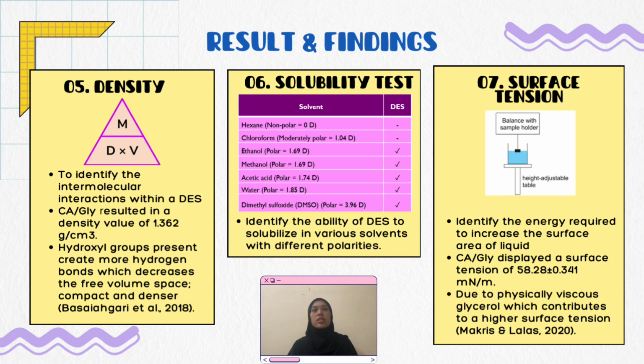The final characterization is the surface tension test. So this test is to determine the external energy required to increase the surface area of a liquid in a fixed volume. The chosen DES had displayed a high surface tension of 58.28. Apart from glycerol being highly viscous in nature, the surface tension mainly arises from generations of electrostatic forces, van der Waals interactions, and hydrogen bonding. Overall, it can be observed that the high physicochemical properties can be easily adapted through elevated temperatures and dilutions for extraction purposes.